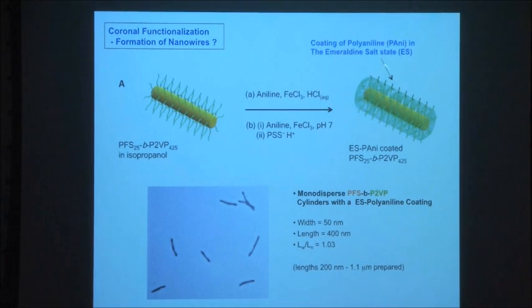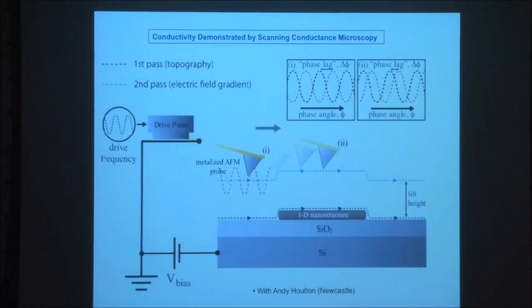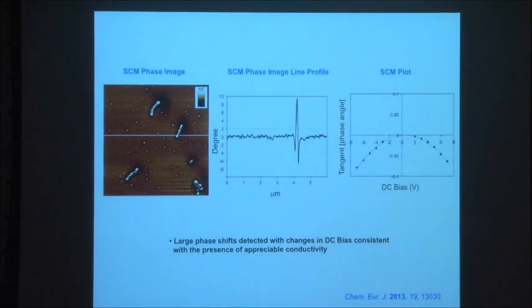Now, a key thing is that we're saying this is a nanowire. Does it actually conduct electricity? Is it conductive? We've looked at this using a non-contact mode approach in collaboration with Andy Houlton at Newcastle in the UK. We use the method of scanning conductance microscopy, where in tapping mode, you look at a phase image of the structure in the presence of a potential difference between the tip and the substrate. And if you have a conductive material, you see a change in the phase angle when you apply the DC bias.